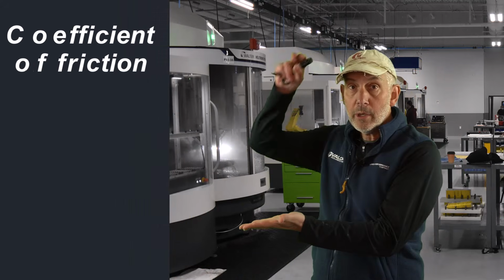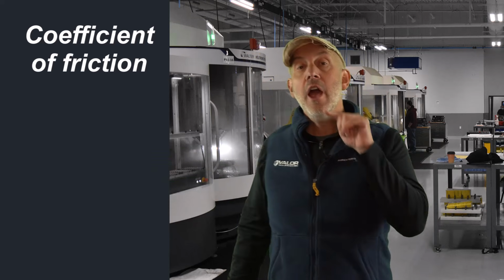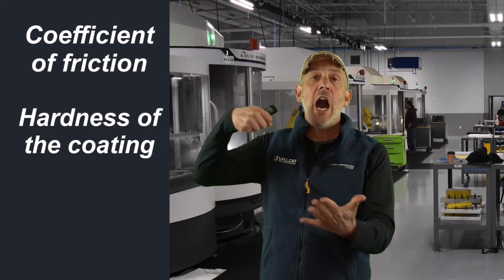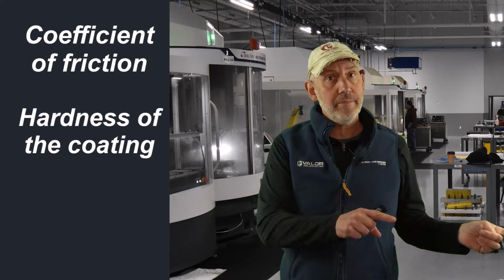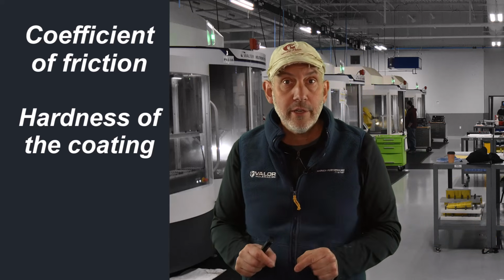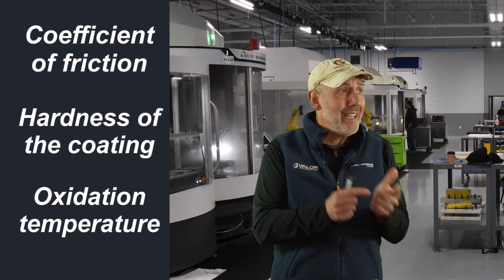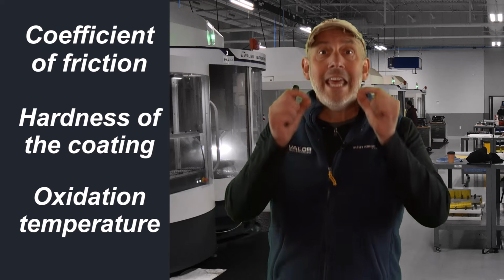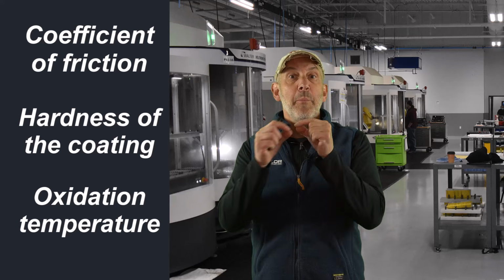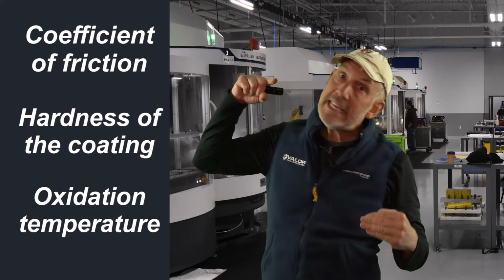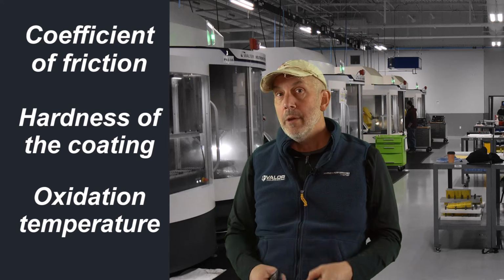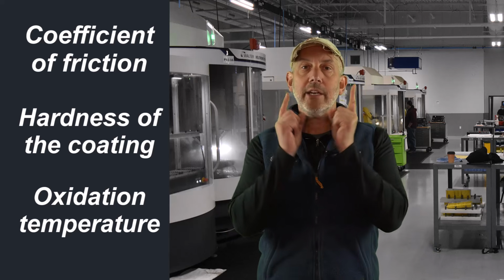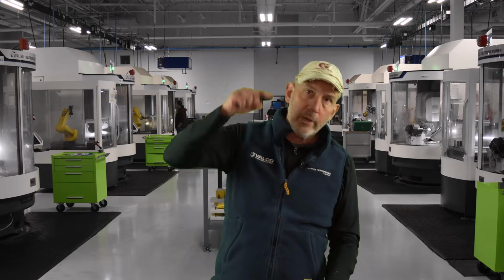So we talked about the main parts of coatings, right? The three things. Hopefully you understand it. Coefficient of friction, the ability of the chip to flow on the coating. That's coefficient of friction. Vickers hardness. Vickers hardness is a different scale. How hard is that coating? You need it very hard for very abrasive materials. Make sure you're mindful of how hard that material is. Oxidation temperature. How hot can I get that coating before I start degrading the quality of the coating, introducing oxides to it, breaking it down? We don't want that. The higher the temperature, the easier or the better it is to run a little bit faster, be a little bit more productive, and also work with materials that cause the most amount of damage to your cutting tool. So, put a coating on your cutting tools. Not all the time, but most of the time. And you'll be happy you did.